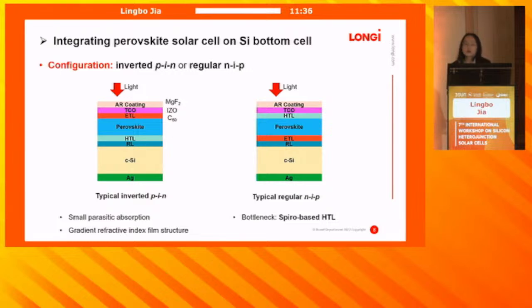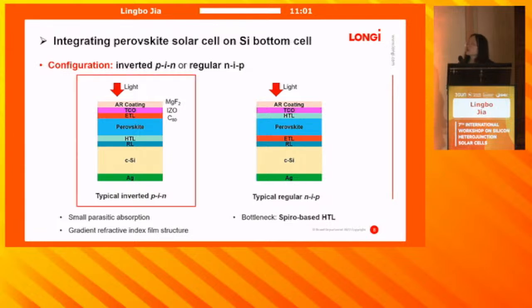First, as we know, there are two configurations of tandem solar cells, the inverted and the regular structure. The inverted structure has many advantages, including lower parasitic absorption and a gradient refractive index film structure, leading to higher device performance. In contrast, the regular structure usually utilizes a spiro-based HTL, which can lead to additional parasitic absorption and also induce instability issues of the perovskite surface. So here we choose the inverted structure to fabricate the tandem solar cells.